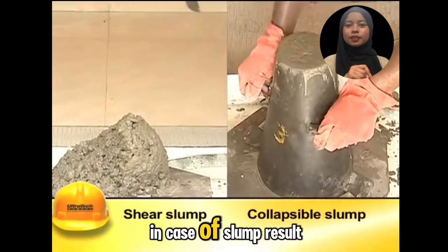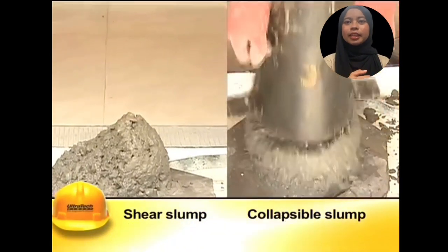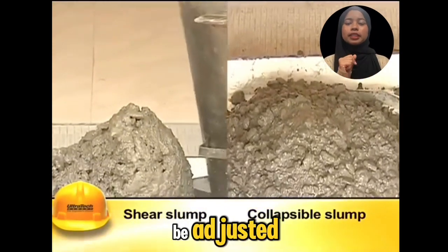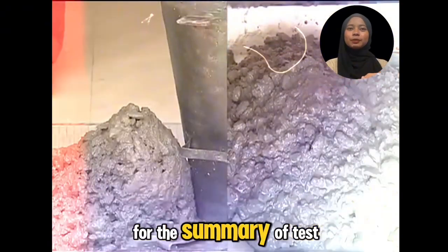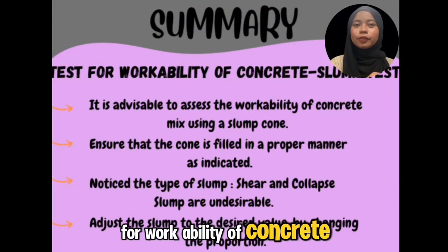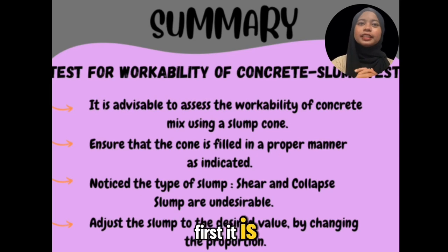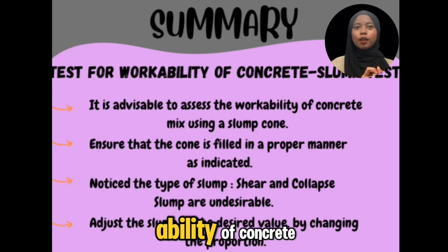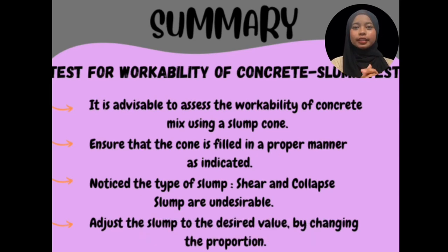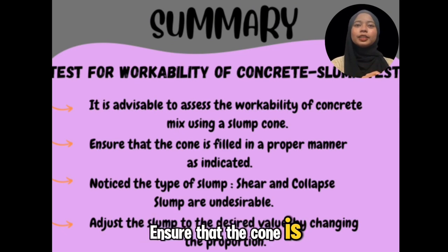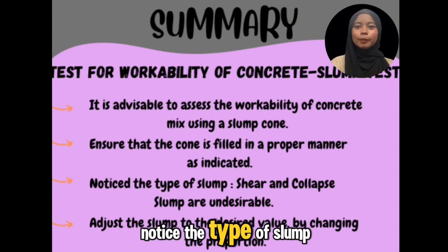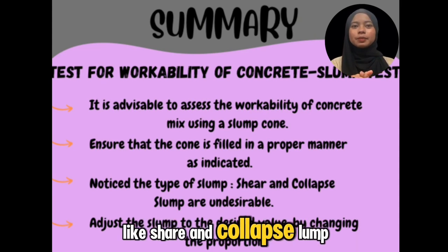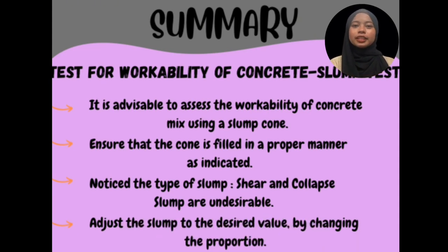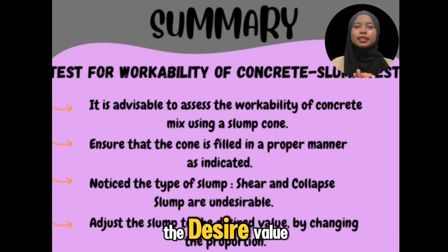In case of slump result beyond the specified limit, the mix proportion needs to be adjusted, especially the water content. For the summary of tests for workability of concrete. First, it is advisable to assess the workability of concrete mix using a slump cone. Second, ensure that the cone is filled in a proper manner as indicated. Third, notice the type of slump. Shear and collapse slump are undesirable. Lastly, adjust the slump to the desired value by changing the proportion.